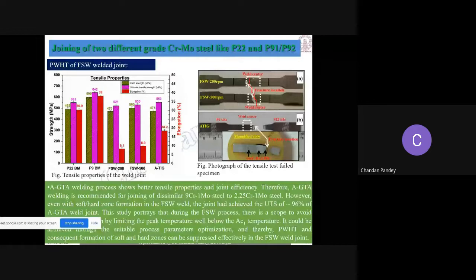And for different types of joints, if we talk about friction stir welding, as we discussed, due to improper mixing in the region of your weld metal, we get the failure from the region of your weld metal. We get the failure, not in service, but in the as-welded condition. If we perform the tensile test, we get the failure from the region of your weld metal, and we get a tensile strength lower than the strength of the base metal. So in that case, we don't prefer that type of joint. That is the problem related with friction stir welding if you are going to use it for steel plate and steel material. Now, come to your service condition.